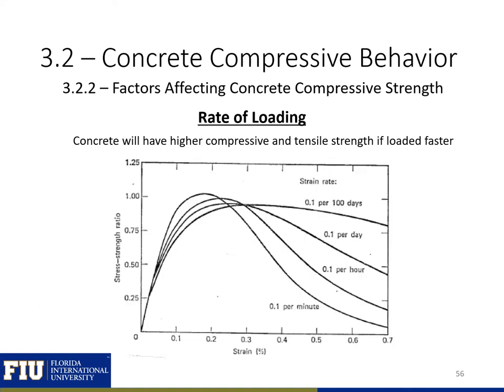Here are the stress strain curves for concrete loaded at four different strain rates. Faster loading resulted in a higher compressive strength, a lower strain at ultimate strength, a steeper descending branch after the ultimate strength was reached, and less ductility. Again, the most important point is that concrete will have a higher compressive and tensile strength if loaded faster.